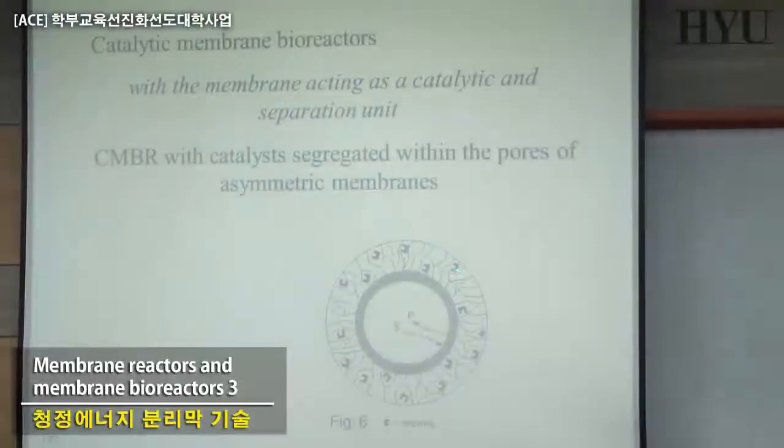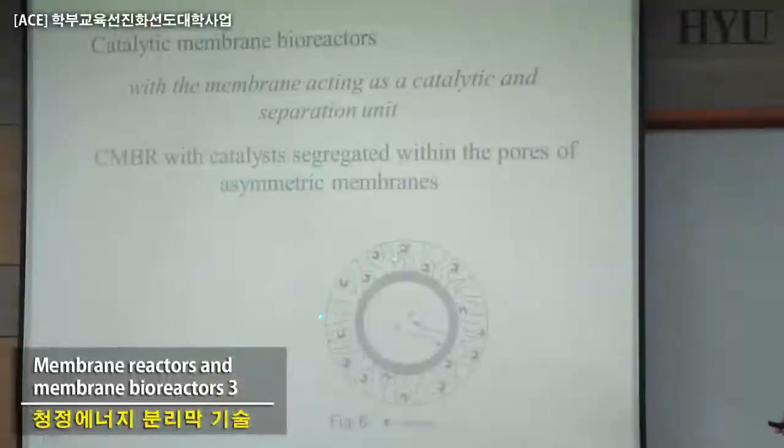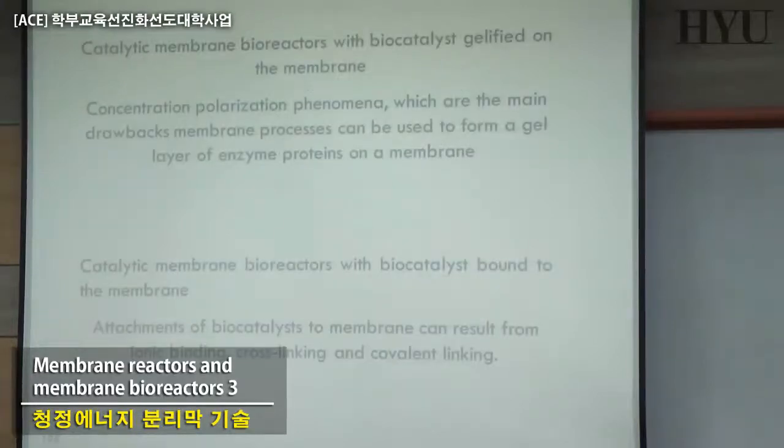On the other side, there is the risk that you can remove the enzyme from here much faster if you have pressure drops in this direction, but normally you are able to control that. What you have to be careful about is that the amount here is not infinite. Normally it can be on the order of 20%, 30%, 40%; more than 40% you can start to have some leakage, and that is not what you're looking for. But there are different ways of doing it and of controlling this kind of situation.